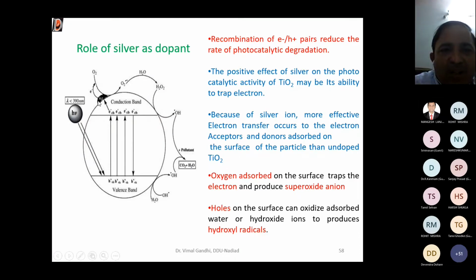Silver sits on the surface of the photocatalyst. Earlier, in the absence of silver, an electron is transferred from the valence band to the conduction band, and the electron takes part in photoreduction, and the hole takes care of photooxidation, but they recombine again. That recombination rate of electron and hole is very fast, even in nanoseconds. So you have to change that rate to increase the performance of the photocatalyst, and that's why we put silver here. Silver works as an intermediate step because it is Ag plus. The electron has a negative charge, so it is attracted towards silver, and you reduce the rate of recombination in this silver-doped material, and that's why you get very good results, as reflected on this slide. So this is the role of silver, and we reported it in more detail in our published article.